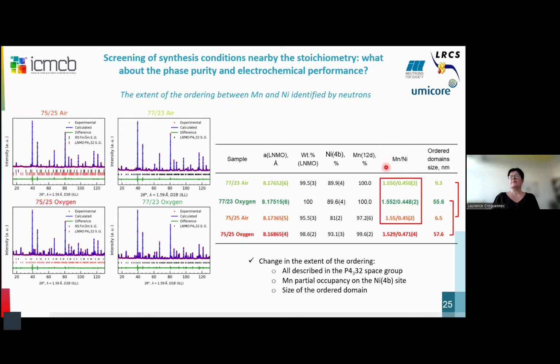We have a manganese site that is full of manganese, and we have a mixing in the nickel site between manganese and nickel, of course manganese 3+ and nickel 2+. But you can see that depending on the atmosphere, in similar annealing conditions, we can have a difference in the size of the ordered domain that I had associated to the superstructure line broadening here.